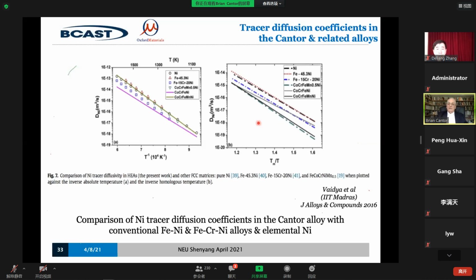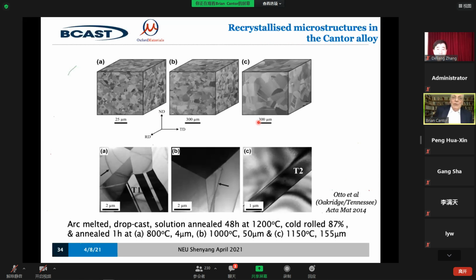Let me go on now to talk a little bit about, when I can get the next slide to come up. There we go, the mechanical properties and the slip behavior. So Otto et al., who are partly at Oak Ridge and partly at the University of Tennessee, did some very beautiful experiments. They made the 5-component Cantor alloy and recrystallized it for different times to get 3 different grain sizes, as you can see here. Equiaxed grain sizes, very nice, beautiful structures. If you look in the electron microscope, they consist of grains which are very clean, with the occasional annealing twin.